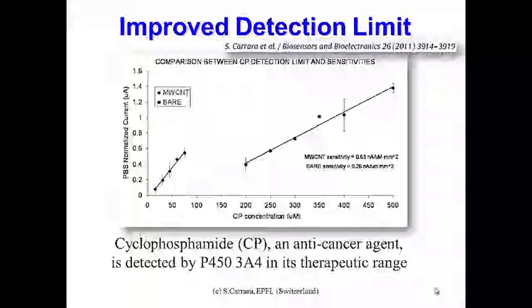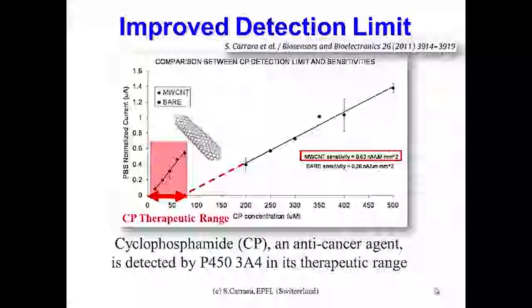Of course, our aim is not to decorate the electrodes, but to improve the performance of our sensor. And we can just have a look at this graph. This graph summarizes the detection of a very well-known anti-cancer compound, cyclophosphamide, as detected by using, again, the isoform 3A4 of the cytochrome P450. And as you can see, we get two calibration curves, but in case we do not include the nanotubes in the electrochemical interface, we reach a limit of detection that is beyond the therapeutic range we would like to address in the case of cyclophosphamide. While we can indeed succeed in fitting the required window of concentrations if we have in our electrochemical interface the multi-walled carbon nanotubes. So in this example, the use of carbon nanotubes made a difference.